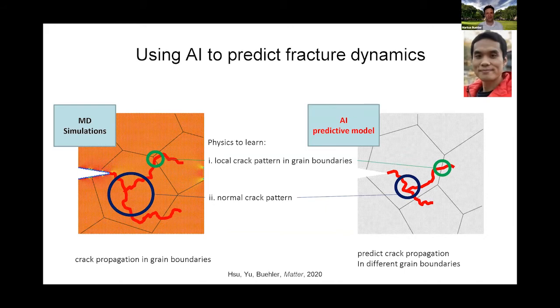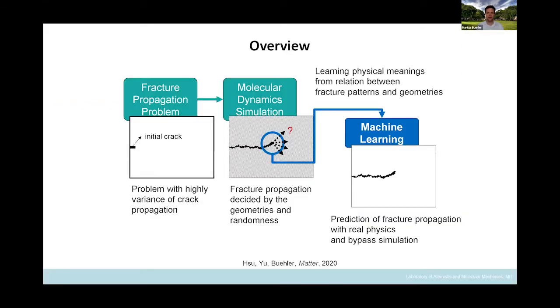So Johnny, my postdoc, who is shown on the right-hand side on the top, has been looking at this problem. And Johnny has thought about a way of creating a data set, a training set to teach an AI system to remember, to predict how cracks propagate. And the way we do this is we start very similar to what we've done before. We have a training set that basically consists of observations of crack propagations in many different material configurations, many different crack orientations, different crystal orientations, different boundary conditions, obtained by molecular dynamics simulations. So we simulate atom by atom how these cracks propagate, and then use this data set to train a machine learning model to learn these relationships.